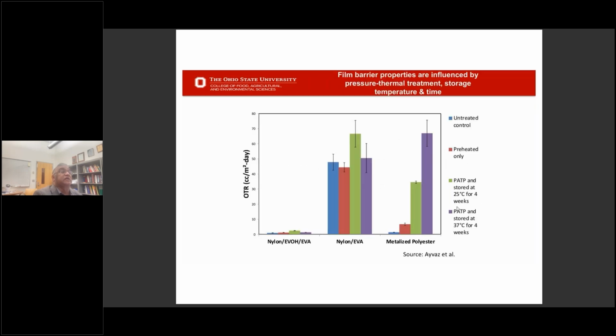This slide just shows different packaging materials, nylon, EVOH, EVA, metallized polyester, and their oxygen permeability. What you see is that for certain packaging materials like metallized polyester and nylon, the barrier properties are significantly affected compared to EVOH and EVA, where the treatment doesn't affect the barrier properties. So you need to pay attention because these food materials have a longer shelf life. If the barrier properties change, that can affect the shelf life of your product. Next slide, please.